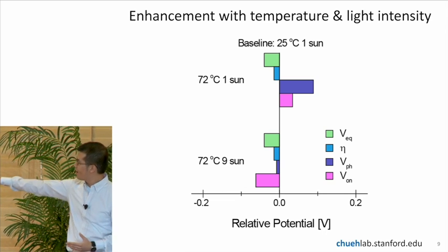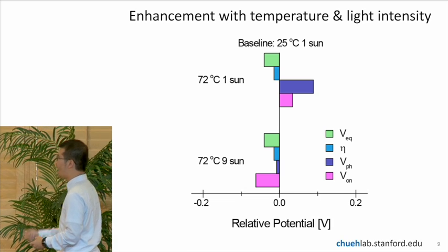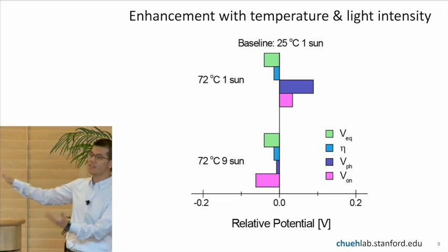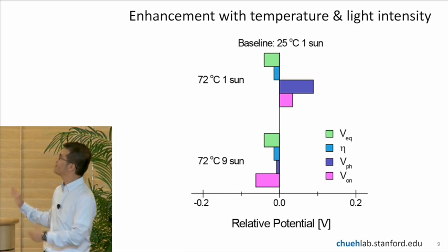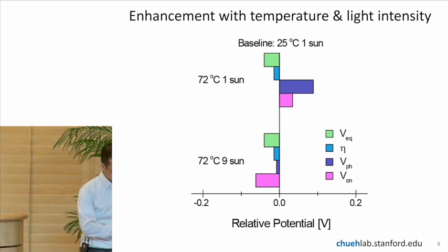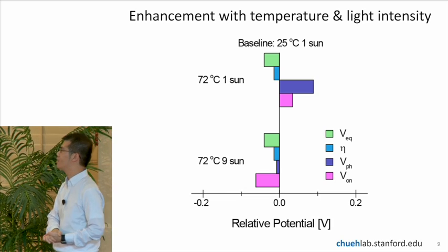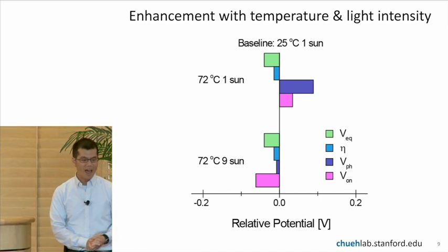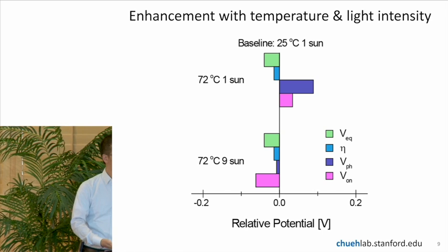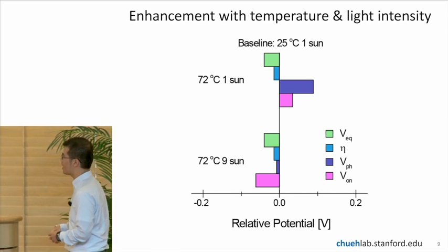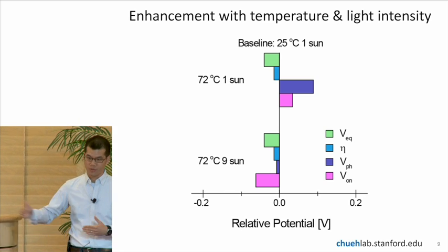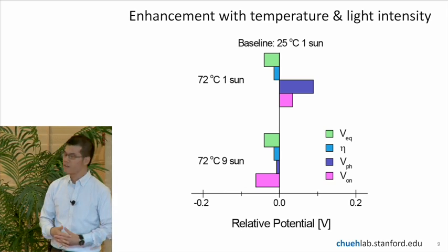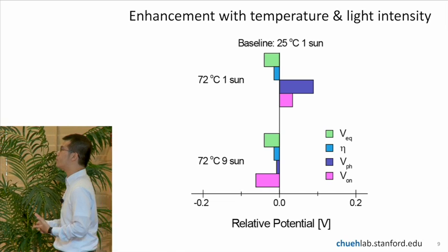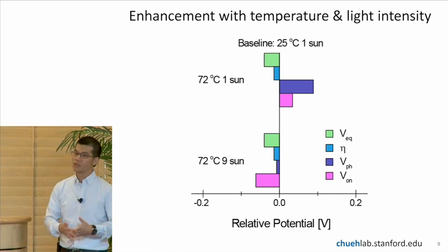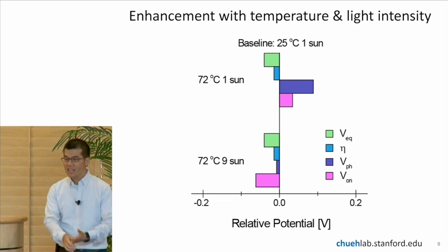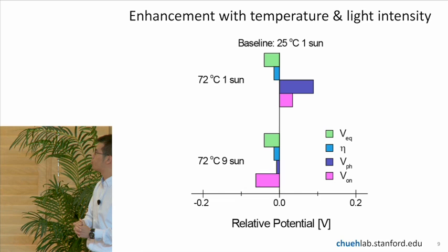But on the second row, where we have increased temperature and increased optical concentration, then we have everything moving in the right direction. Sorry, that means everything moving in the right direction to the left. So you have the thermodynamic driving force needed decreasing. You have the overpotential required decreasing. You have the photovoltage actually increasing slightly. And then you have the overall onset potential, so this is where the current starts to take off, also decreasing by about 70 millivolt. So this is a considerable first step to demonstrate that it is a good idea to put in light and heat into the photoelectrochemical cell to improve the efficiency.